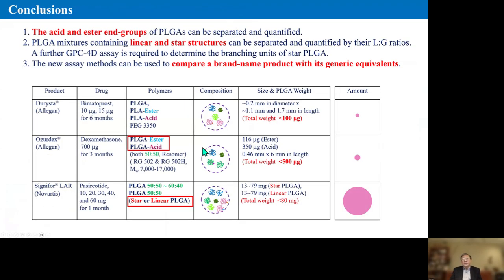So in conclusion, today I just want to mention that we can assay the contents of acid end group or ester end group, even if they are mixed and the LG ratio is similar, molecular weight is similar. So we also present here today Signifor LAR. We can separate the star-shaped PLGA and linear PLGAs based on the semi-solvent approach. Now our remaining job is to further characterize Signifor LAR based on the exact quantity of the star-shaped or linear PLGA.